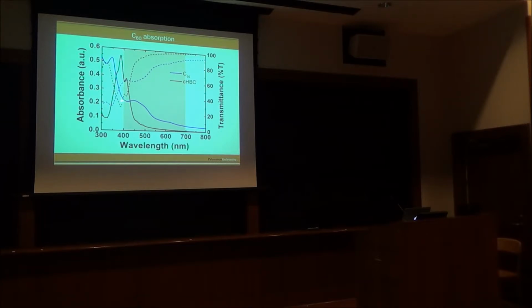And you can see that C60 absorbs quite a bit in the visible. The transmittance curve is in the dashed line, and you can see that with C60, you're absorbing a lot of the visible here. So we need to replace C60 as the acceptor.